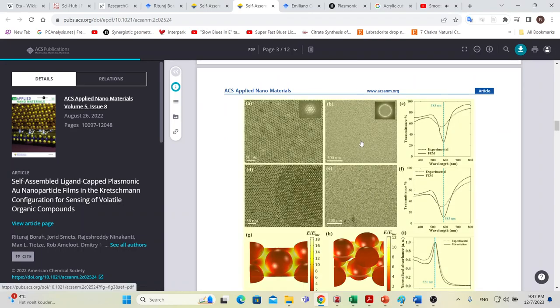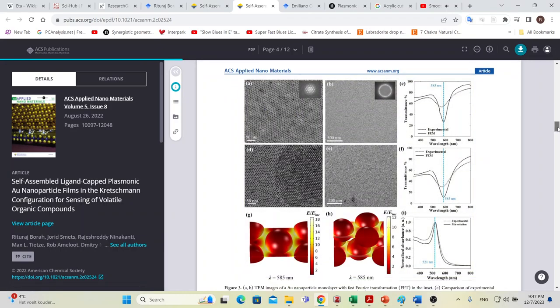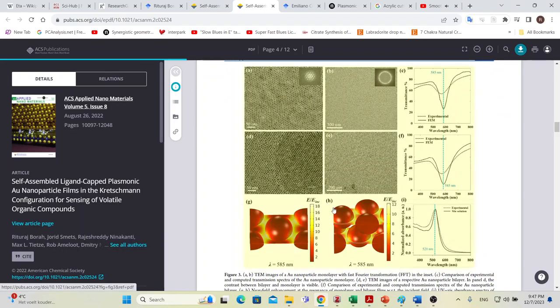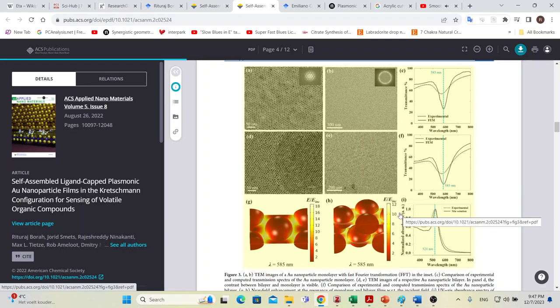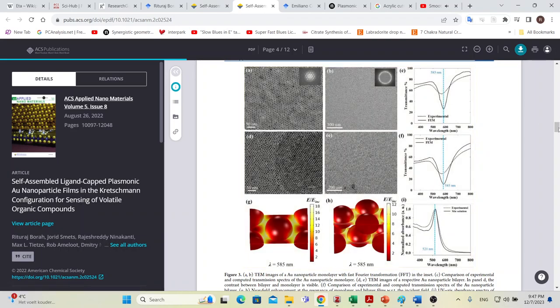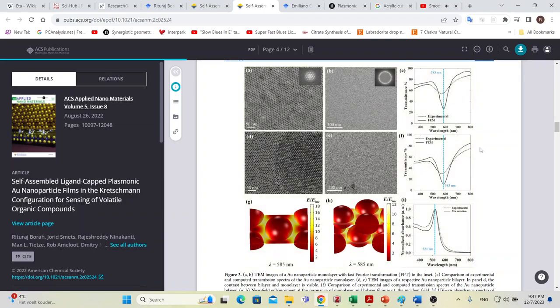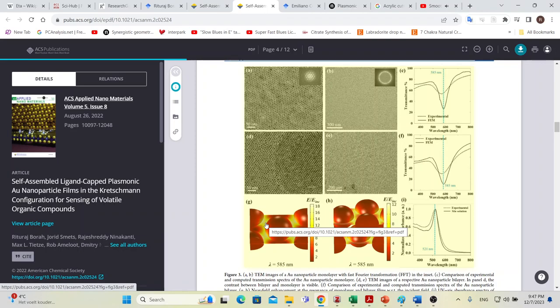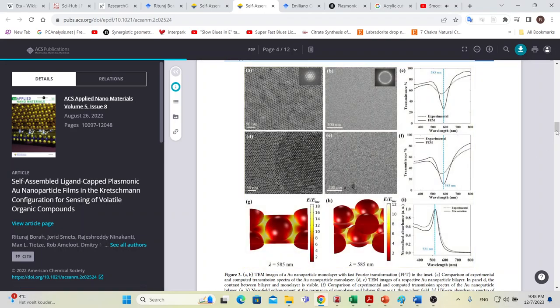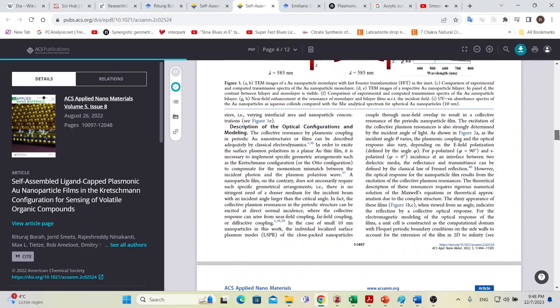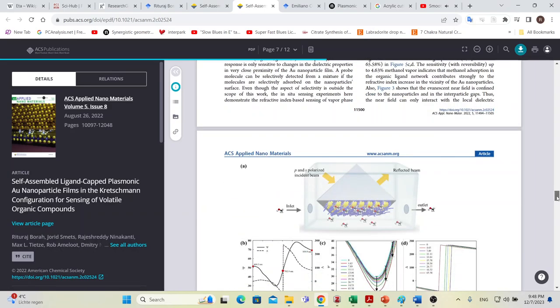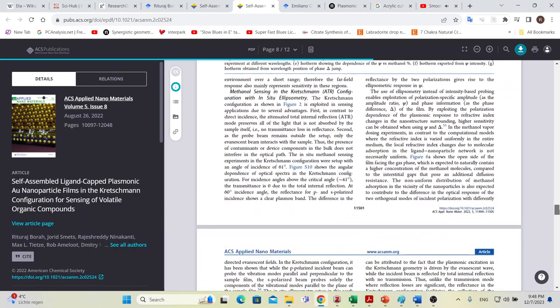When it is characterized with TEM transmission electron microscopy, you can see that these nanoparticle films are highly ordered over long distance. I also did the electromagnetic modeling of these nanoparticles using the unit cell approach. I've actually shown in my previous videos how to do these kind of modelings. With this kind of modeling you can find the far-field properties like transmission, reflectance, absorptance, and also the light concentration effect, also called the near-field enhancement effect, and how strong it is in the interstitial or inter-nanoparticle gaps.